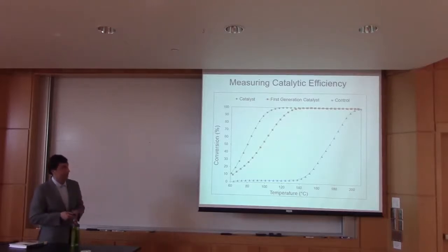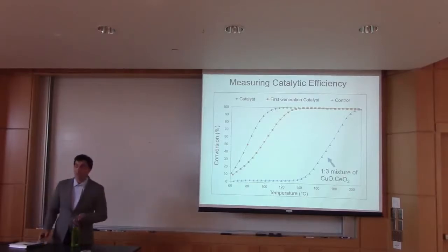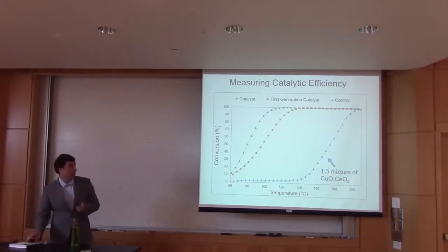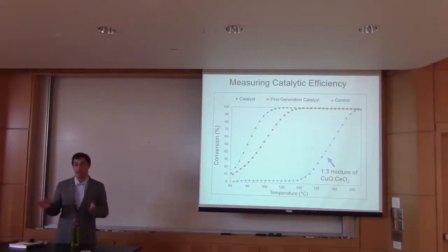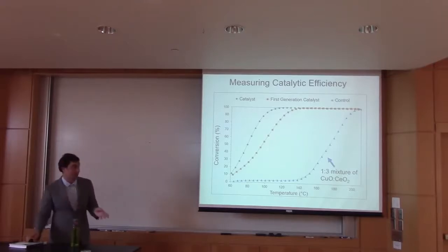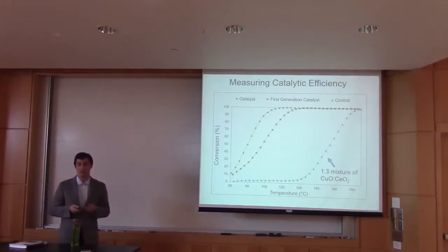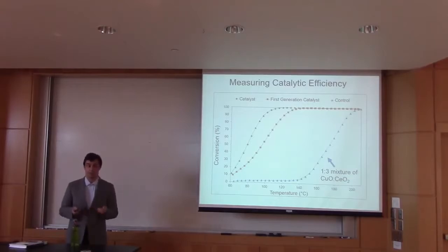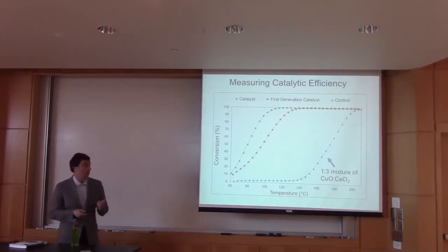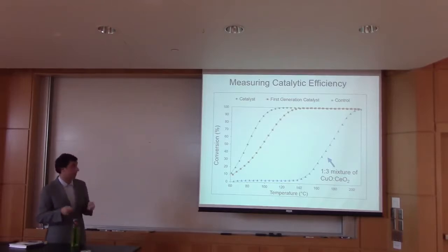So we have three plots, this blue one, this orange one, and this green one. The blue one is a standard. It is a stoichiometric ratio of the metal oxides as we'd expect to see them occur in our catalyst. It's not MOF templated. So I took both metal oxides from a chemical supplier and ground them together. And that's what we use to check and see the efficiency. And what we see is it performs much worse than these two catalyst samples. What this indicates to us is our MOF templating approach is doing something, and we're not looking at the innate reactivity of these metal oxides, which is great.